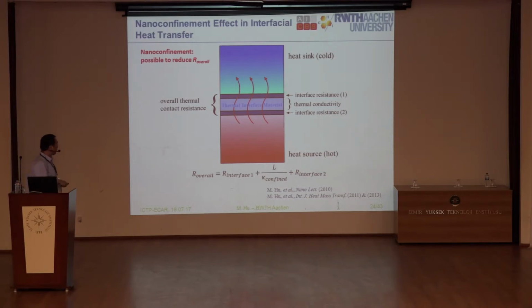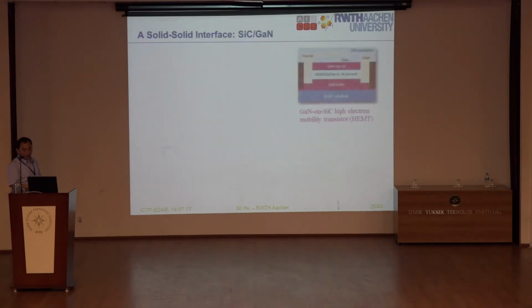So here we found that by carefully choosing some materials in between, and then sometimes by reducing the thickness of the material, you can reduce the overall thermal resistance. So this idea is the first we talk about. We studied this silicon carbide gallium nitride interface.